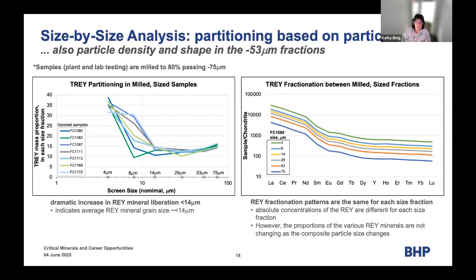And we go down, and there's not a whole lot of difference, 75 microns, 53, 29, we're down into the cyclo size fractions. Once we're below 14 microns, all of a sudden, the mass proportion of those rare earth minerals starts to skyrocket in those remaining size fractions. And you can say, well, either I've ground a very coarse mineral down, or most of those rare earth minerals are naturally down in that size fraction range. So it's a combination of both, but we know by doing more in situ measurements on samples that haven't been subjected to what metallurgists do.